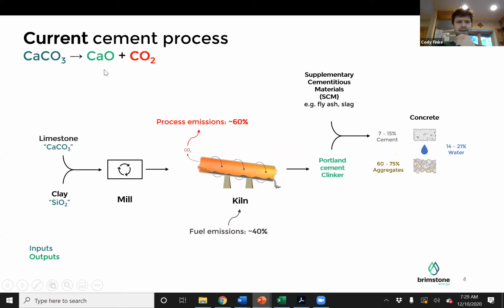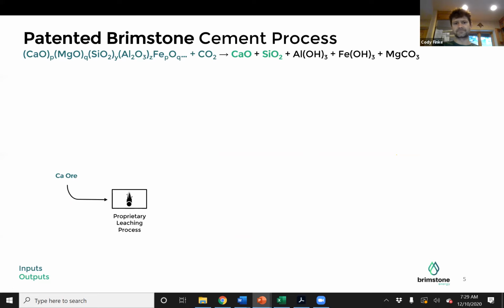One of the things that we noticed is calcium oxide is the key component of cement, of course. And the problem with the CO2 emissions is we've chosen a source of calcium oxide that is bound to CO2. What we can do in our process is start with a calcium silicate. So a rock that has a lot of calcium in it, but doesn't have any CO2 bound to it. We go through a proprietary leaching process, and what comes out of this leaching process is calcium oxide, as well as amorphous silica, so supplemental cementitious materials.